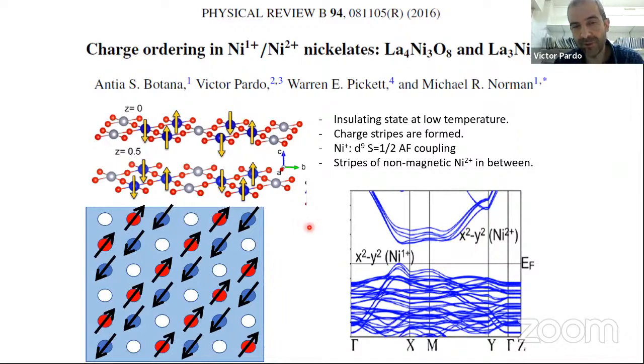So this is like kind of a charge order situation that opens a gap. So at low temperature, you don't have the low spin solution. You have a competition between different charge and spin states. This nickel 2 plus is low spin, and this nickel 1 plus is spin a half, like in the cuprates. So our prediction was that this was the structural pattern, but also with the structural pattern there was a charge order and a spin order. So this was what we predicted, that these stripes would be magnetic in this way.